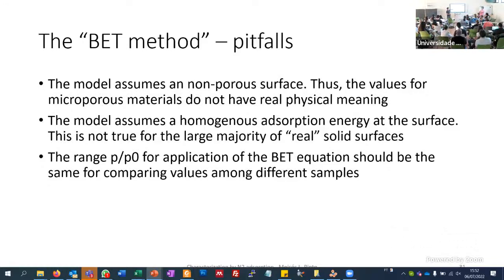The range of P over P0 for the BET equation should be the same for comparing values among the different samples. As you have seen, if you put one more or less value, the value also changes. So if you have a batch of samples and you want to compare them, you should at least try to use the same range of P over P0. Otherwise, you have some differences that are because of the different ranges selected. And as you have seen here, if you want to measure the surface area of the material, you don't even need to measure the full isotherm. You can eventually just measure on this range.